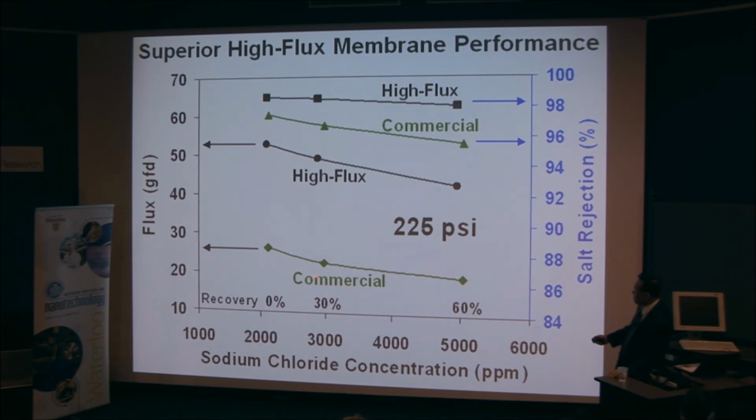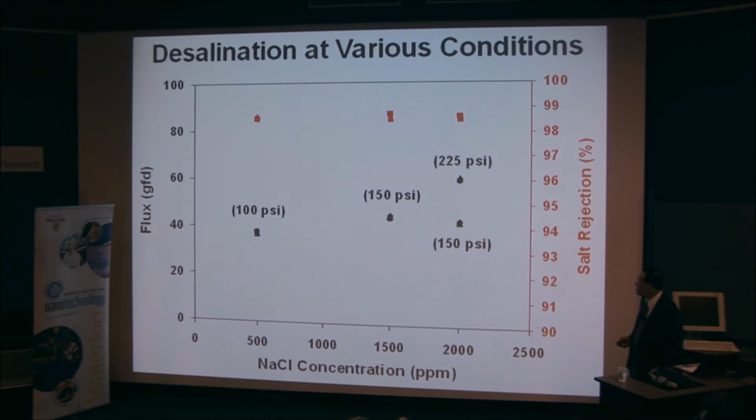Versus the commercial membrane, the sample we obtained from a company, we show a significant increase in the flux. We essentially about double, and the salt rejection is also better.